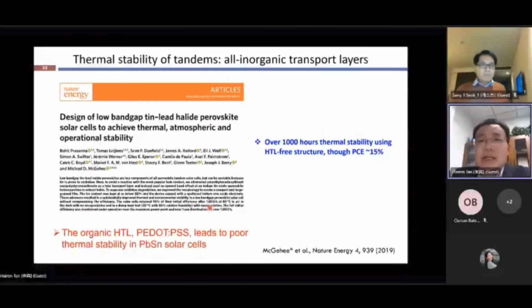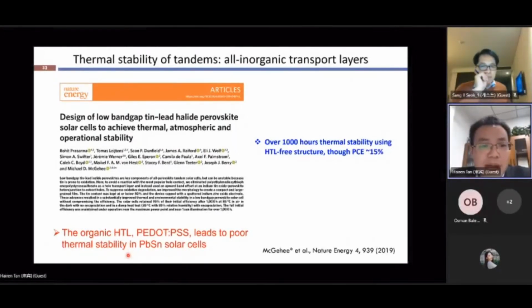Another thing we have to think about is the thermal stability of the all-perovskite tandem devices. For all the high-efficiency narrow-bandgap perovskite solar cells, we have to use an organic hole transport layer, which we call PEDOT:PSS. From Professor Michael McGehee's group, we found that this PEDOT-based hole transport material leads to very poor thermal stability, because the interface between the PEDOT and the mixed lead-tin perovskite is not thermally stable.